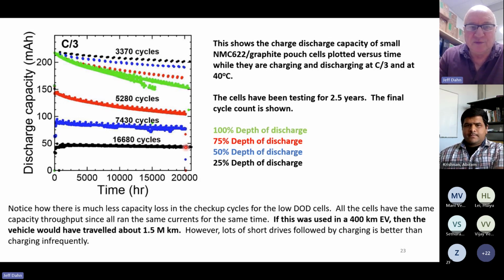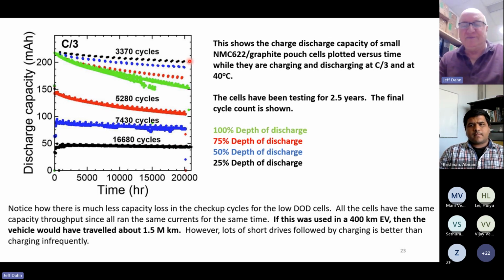Now, one thing you need to remember is all these cells after 20,000 hours have all passed the same amount of charge in the charge and discharge directions. And doing the small depth of discharge cycles leads to much better capacity retention. And just as a point, if this was used in a 400-kilometer EV, the vehicle would have traveled about 1.5 million kilometers, okay? So even in the green case, it would be fine. But if you're interested in having a lot of battery life remaining, it's better to do a lot of short drives followed by charging.